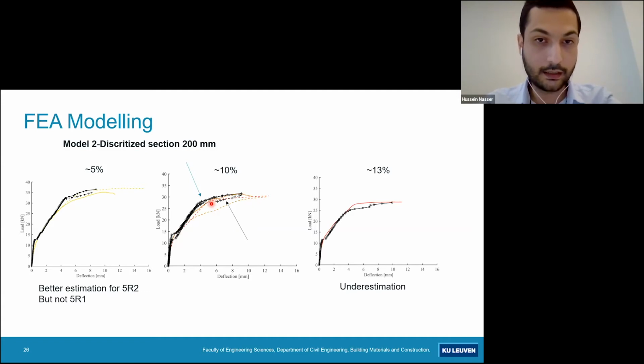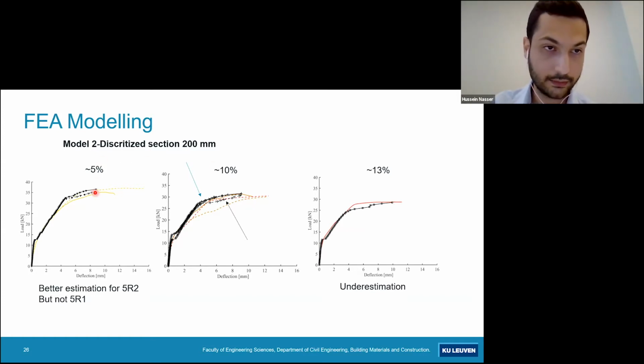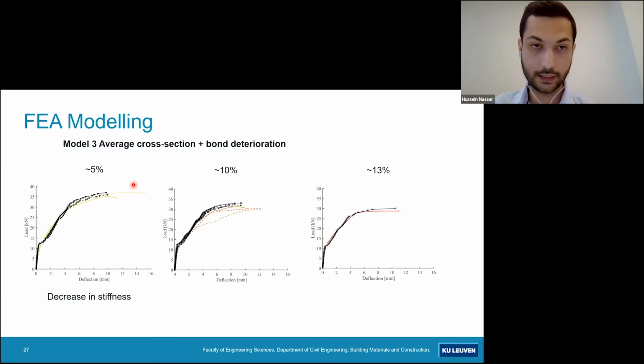So not taking into account the bond deterioration will not affect its results, while for the other beams, the ones shown here, do not agree well with the curves in orange, which showed splitting cracks. Therefore, it's important to take into account the bond deterioration in order to model the decrease in stiffness and the formation of splitting cracks. For the 5%, a better estimation has been obtained for the beam that showed a distinct yield point, but not for the one that showed a formation of splitting cracks.